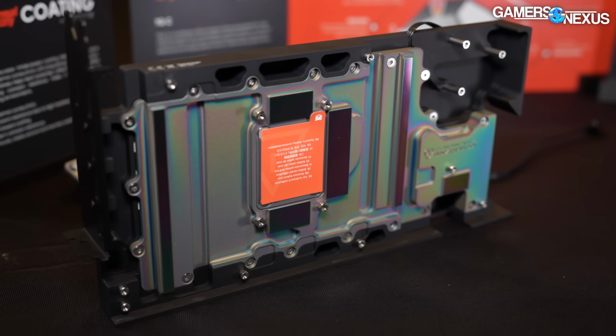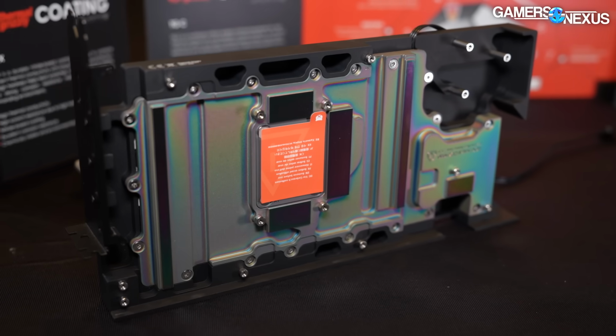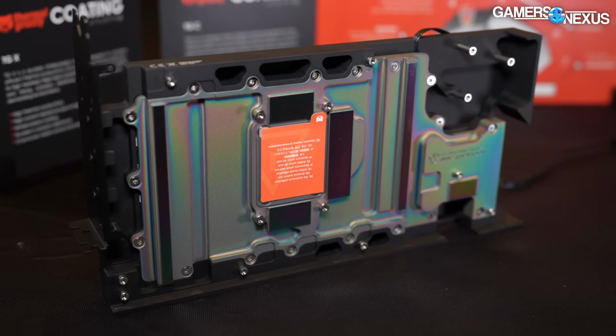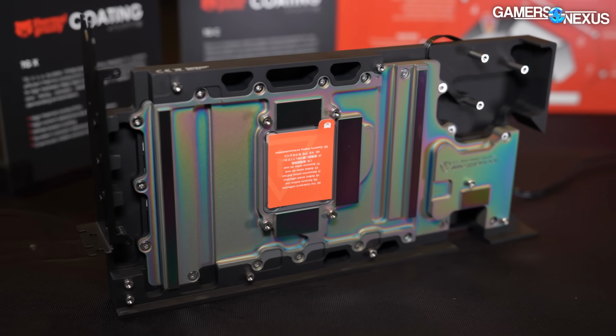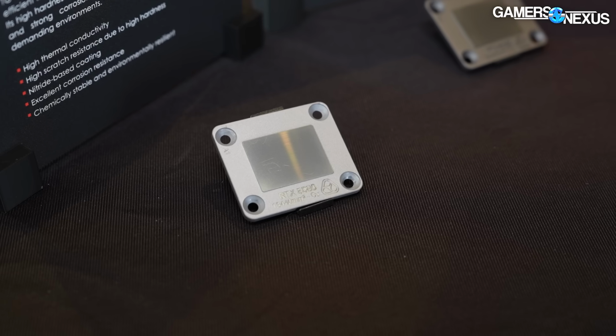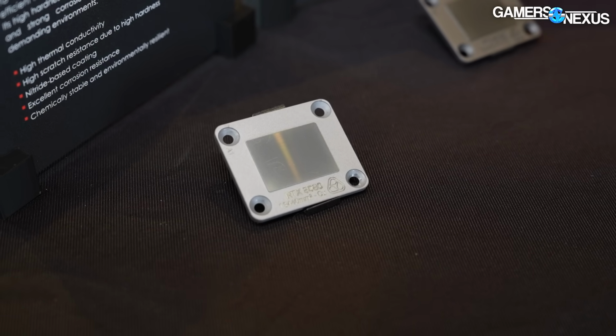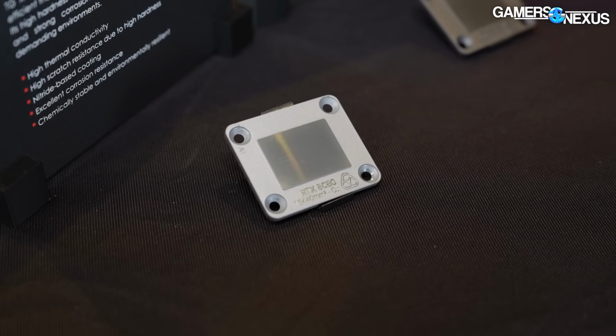What's the impact on your price, I guess, MSRP wise? The pricing will not change much. The difference for us versus an external supplier, the nickel coating, is not much different. These layers are super thin. In typical nickel coating, we're using in the industry between 10 and 20 micrometers, whereas these can be 500 nanometers to 1 micrometer.